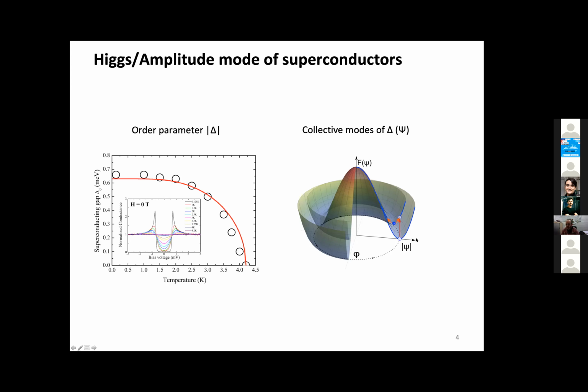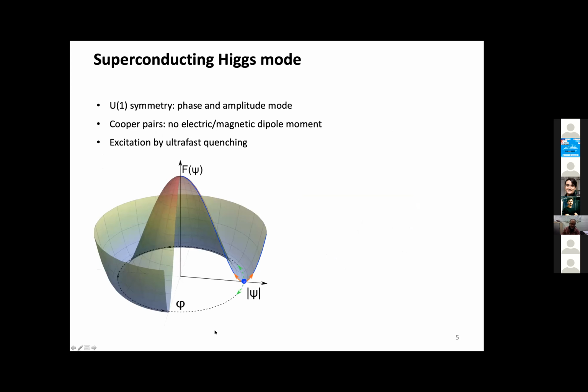The question is now, how can we excite these? And the problem is, since we can't directly drive these Higgs modes because we can't shake this potential around, one option is that we quench this potential. If we come with an ultrafast light pulse that quenches this potential, then we are here in a displaced position, and then we can start oscillating around this new equilibrium position. So that is something that we are showing here. So we are in this equilibrium case. We come with an ultrashort light pulse, we quench this potential, now we are in this displaced position, and then the system starts oscillating around this new position.